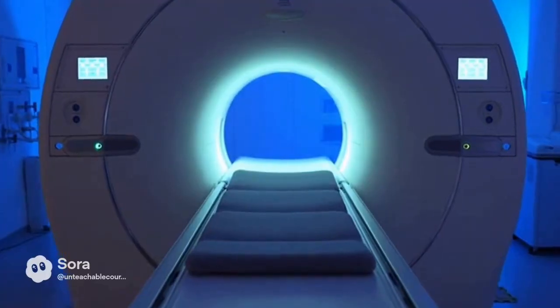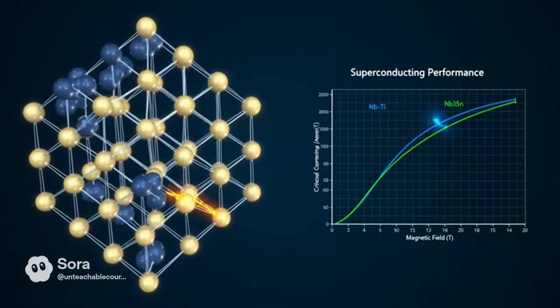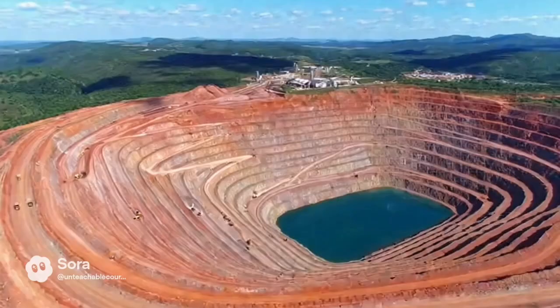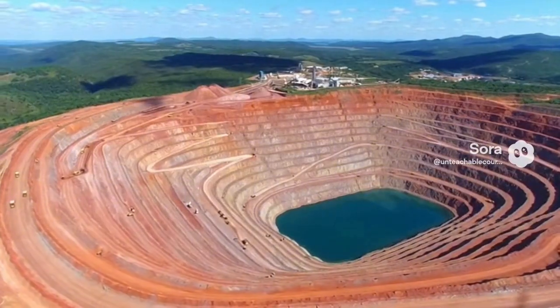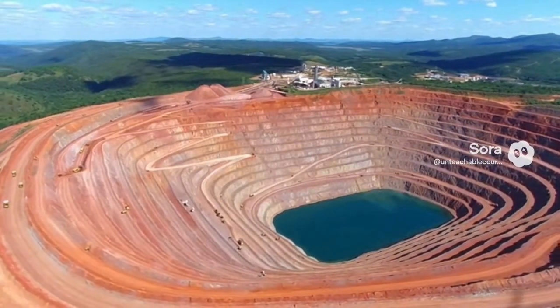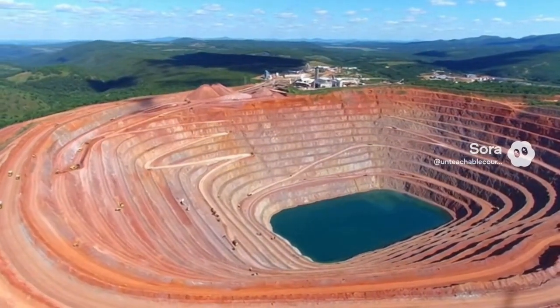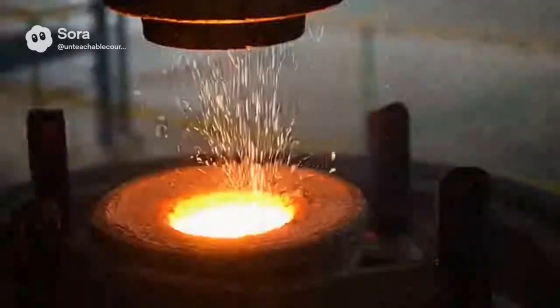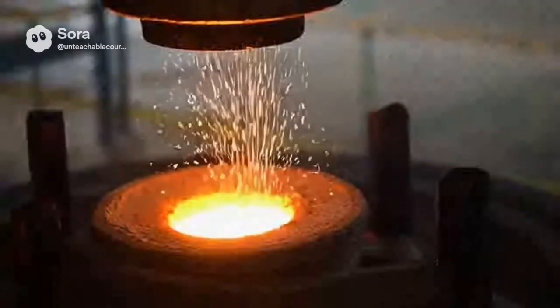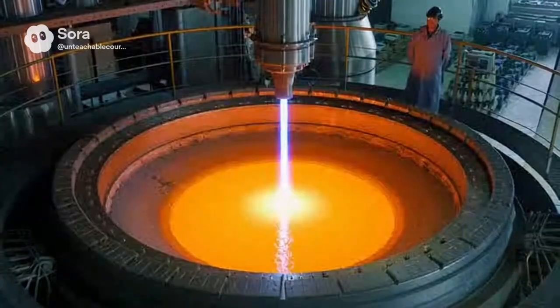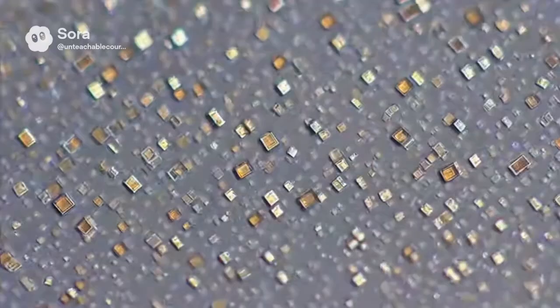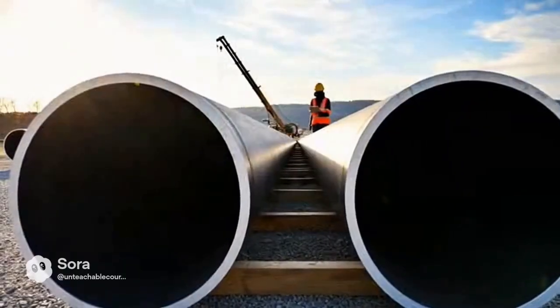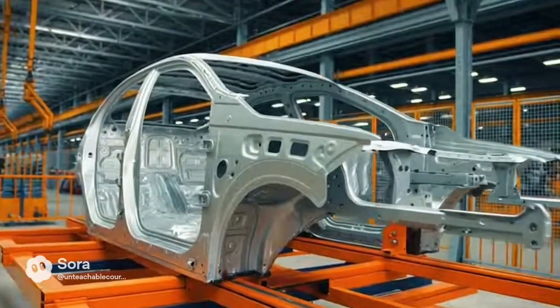It is not the only strengthening mechanism in town. Aluminum and titanium also form their own ordered precipitates, but niobium's presence tunes the balance between strength, ductility, and heat tolerance that designers covet for turbine discs, bolts, and hot section widgets that cannot fail gracefully. Engineers will argue long into the night about which alloy variant belongs where. Niobium is in that conversation not as a celebrity cameo but as a regular.